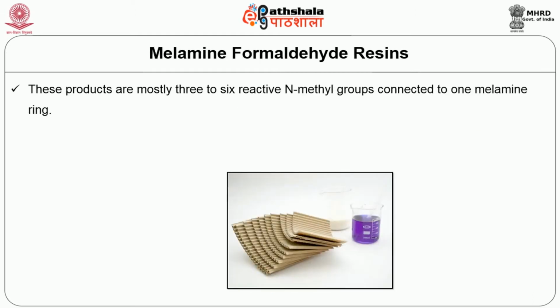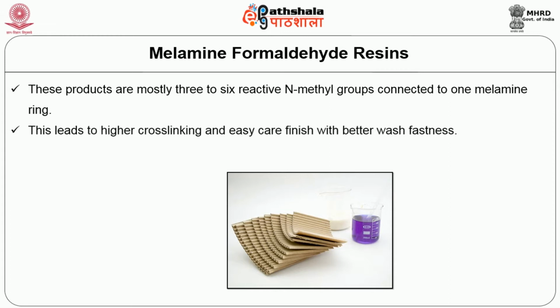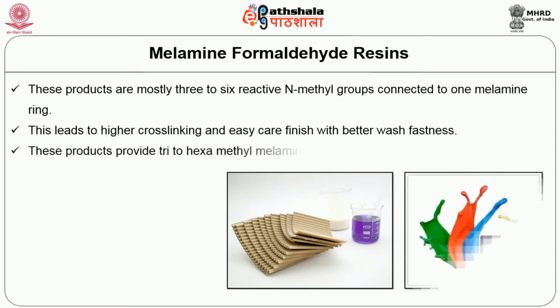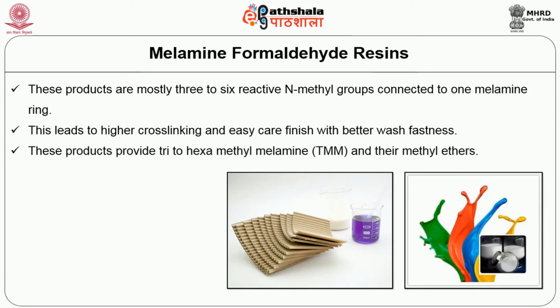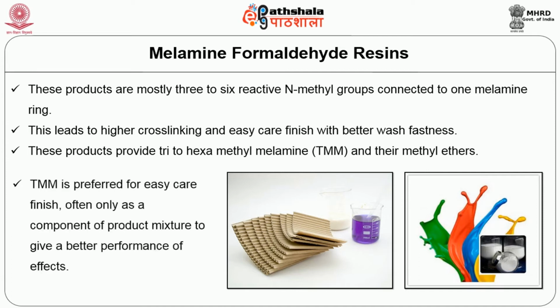Melamine formaldehyde resins. These products mostly have 3 to 6 reactive N-methylol groups connected to one melamine ring. This leads to higher cross-linking and easy care finishing with better wash fastness. These products provide tri to hexamethylol melamine, that is TMM, and their methyl ethers. TMM is preferred for easy care finish, often only as a component of a product mixture to give a better performance of effects.